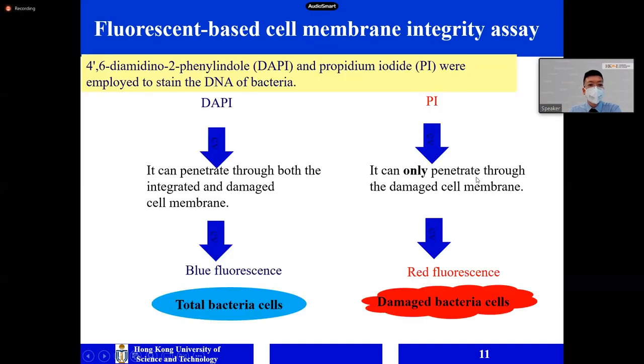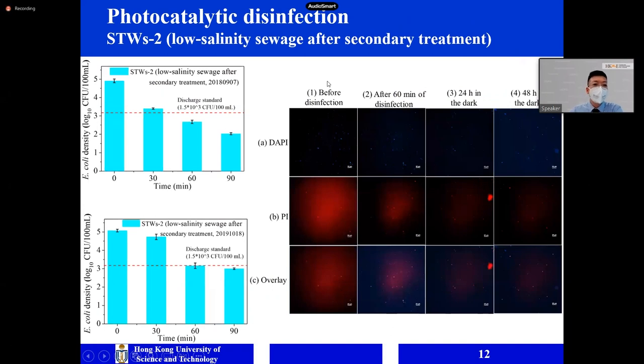The same test was performed on the second type of sewage, the low salinity sewage after secondary treatment, and a promising result was also obtained. After around 45 to 60 minutes, the treated sewage can meet the discharge standard. In the live/dead assay, we can also see no rebound and no significant regrowth of the damaged bacteria after 48 hours in the dark.